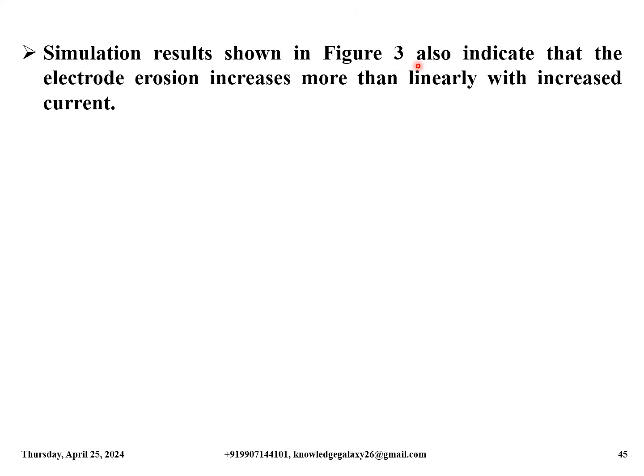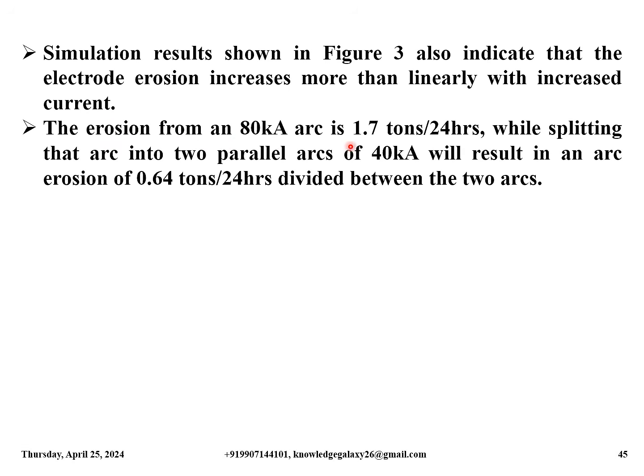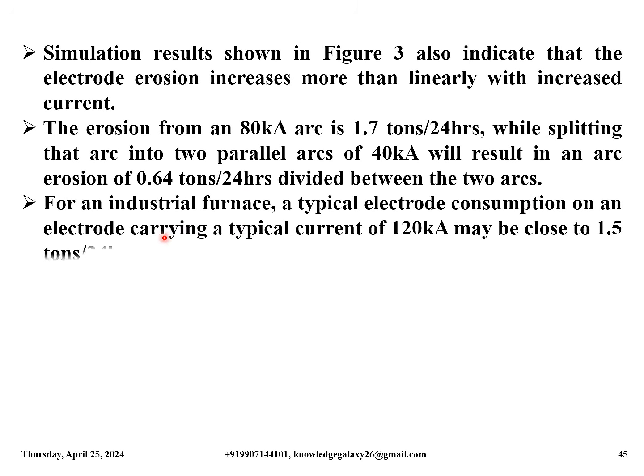Simulation results shown in figure 3. My dear friends, you have to just correlate the previous figure number 3, which I mentioned earlier. Simulation results shown in figure 3 also indicate that the electrode erosion increases more than linearly with increased current. The erosion from an 80 kA arc is 1.7 tons per 24 hours, while splitting that arc into two parallel arcs of 40 kA will result in an arc erosion of 0.64 tons per 24 hours divided between the two arcs. For an industrial furnace, a typical electrode consumption on an electrode carrying a typical current of 120 kA may be close to 1.5 tons per 24 hours.